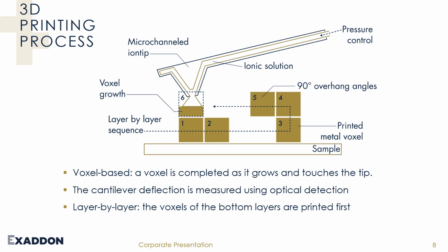From the printing process, again, you see here the voxels, so voxel number 1 and 2, you can print next to each other, you can make gaps, you can make jumps, you can print above each other, you can also do like from 4 to 5, you can make overhangs of 90 degrees with aspect ratio of 100 to 1, so you can go really far to the side without needing any kind of support structures. So pretty much this is the process we have, voxel by voxel and layer by layer.